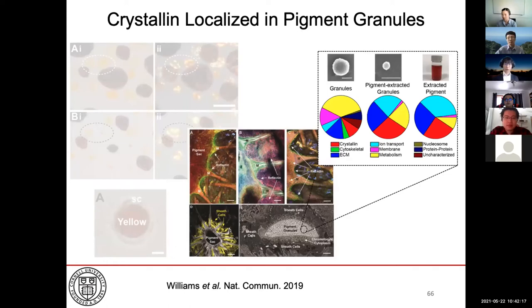Then they extracted the granules from the pigment sac, they extracted the pigments from these granules, and finally they performed proteomics across these three different elements. And here we find another key piece of the puzzle. Another protein called crystallin is found to be heavily localized in the granules. So what this means is that we have a very distinct localization of two different sorts of proteins. Firstly, we have our reflectin in the sheath cells, and we have crystallin in the pigment granules. Now, the function of reflectin is pretty clear from what I've mentioned, right? They form periodic structures to act as a diffraction grating.